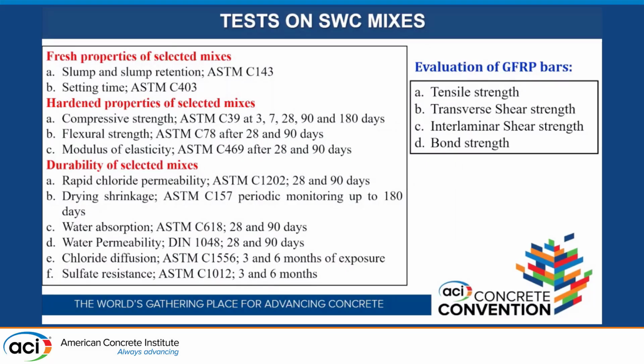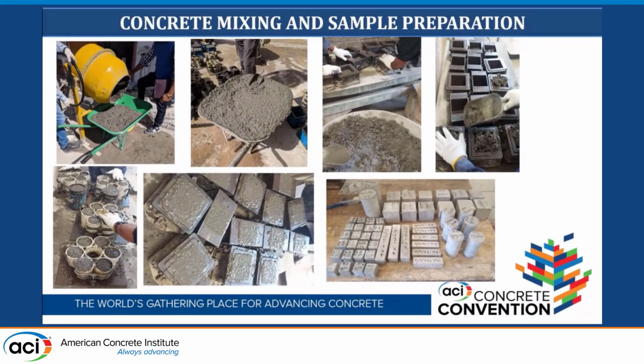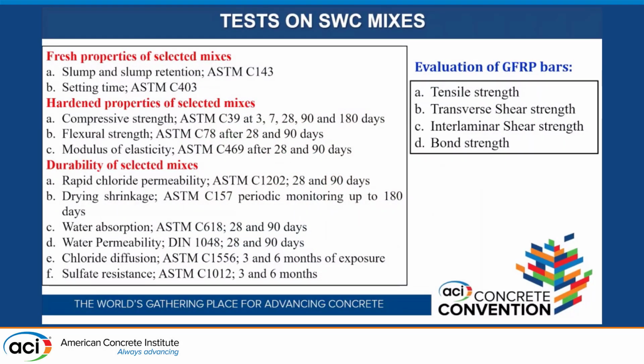Then a large number of tests were conducted: fresh properties of selected mixes, then hardened properties of those selected mixes, and then a detailed durability investigation, including rapid chloride permeability, drying shrinkage, water absorption, water permeability, chloride diffusion, and sulfate resistance. Other than that, in order to ascertain the performance of this concrete and the performance of GFRP bars in this concrete, we embedded the GFRP bars in this concrete, and after a certain period of time, we took out those bars and evaluated the tensile strength, transverse shear strength, interlaminar shear strength, and the bond strength of the GFRP bars in this concrete.